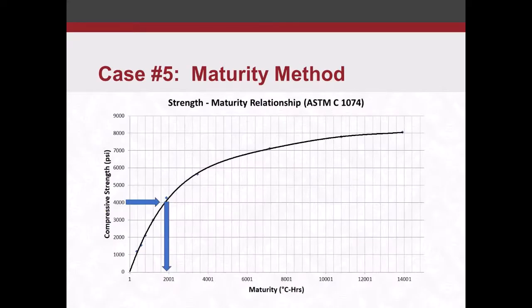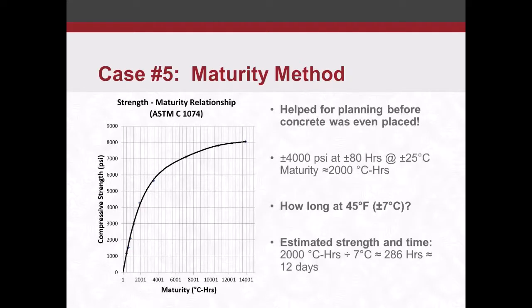On our particular project we used this on, this is the curve we got. It's a beautiful curve. 4,000 psi was the strength we were looking for. We got that at about 2,000 degree hours. So we knew what our maturity value needed to be, about 2,000 degree hours.